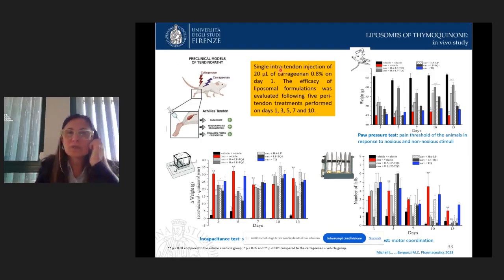After the administration, we produced the inflammation by injection of carrageenan. Then we tested the efficacy of the liposomal formulation following 5 peritendon treatments performed at days 1, 3, 5, 7, and 10. The tests are behavioral tests, and at different times, my colleague pharmacologist performed the paw pressure test to evidence the pain threshold of animals in response to noxious and non-noxious stimuli. Also, to check the motor coordination, the rotarod test was performed, and also the incapacitance test. In gray, there are the results related to the formulations with hyaluronic acid. We tested also one of the formulations without hyaluronic acid, the carrier without the drug, and also the drug, thymoquinone, alone without the formulations.